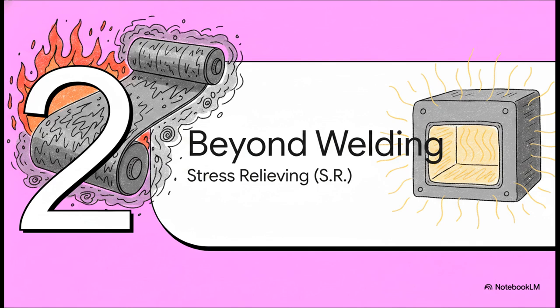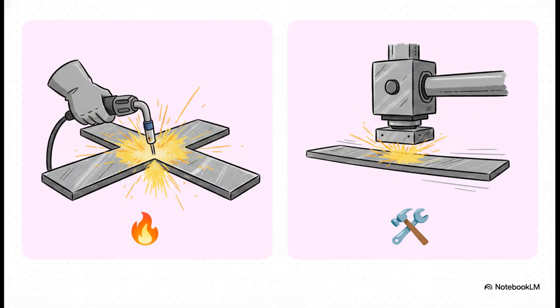Beyond welding, stress relieving, or SR, for mechanical deformation. Now, welding actually isn't the only way to trap dangerous stress inside metal. Physically forcing thick steel into a new shape causes the exact same type of internal chaos. It's important to clarify the difference here, because the actual time the metal spends in the oven looks totally identical. Post-Weld Heat Treatment, PWHT, is specifically done to relieve the residual stress created by thermal damage, like the extreme heat of a weld. Stress relieving, on the other hand, uses the exact same thermal baking method, but it fixes the mechanical damage caused by aggressive physical bending, pressing, or rolling of the steel.